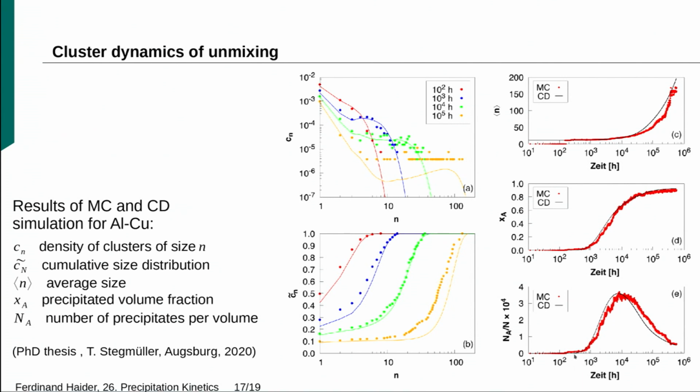And it's interesting to look at this curve here. Here, this is the nucleation phase. Not very much happens. Yeah? And then it abruptly goes up. So you form many small nuclei. And then when this coarsening phase sets in, the number goes down again. And here in this extreme case, you end up just with one huge cluster.